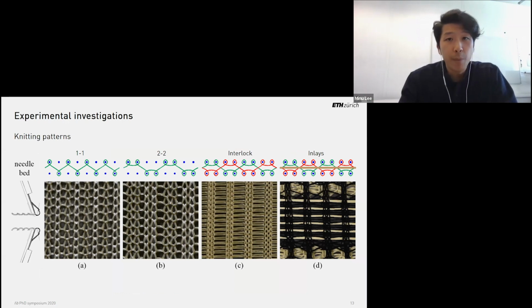We had various parameters that we wanted to study. The CNC knitting machine allows an endless spectrum of different knitting patterns depending on the sequence of needles that you activate to create the loops that will form the textile. In this study, we looked at 4 different knitting patterns. In 3 of them, the 3 on the left side, A, B, C, we used the high-strength aramid yarns directly as knitting yarn to create the textile.